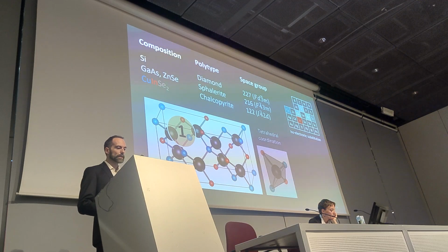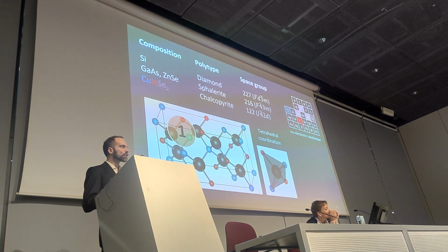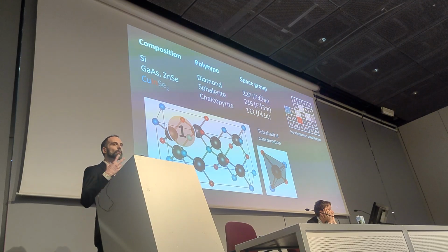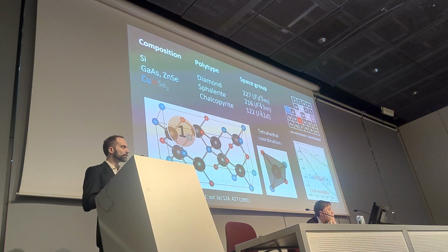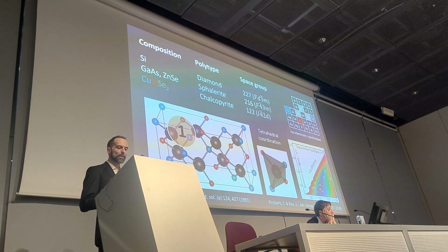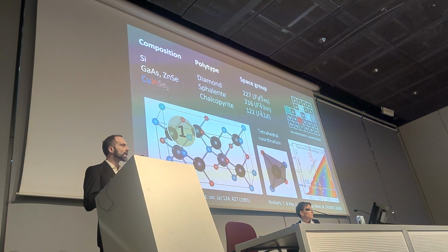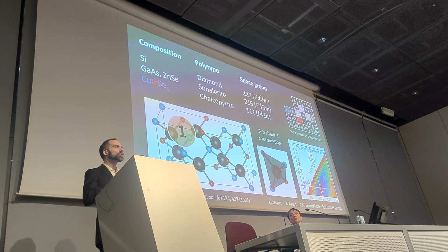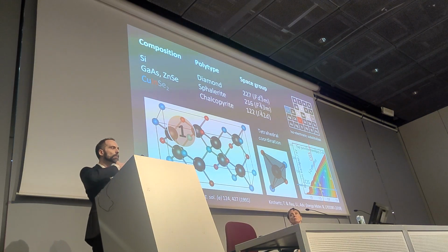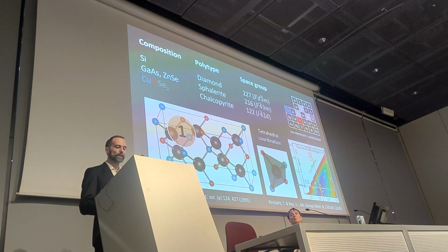Now, every atom in this structure retains the tetrahedral coordination typical for the diamond structure, and here we see a selenium atom coordinated by 2 copper atoms and 2 indium atoms. The very same structure also holds for the copper indium gallium diselenide, so we can replace indium with gallium in a complete miscibility range. And this is important technologically speaking, because the 2 end members, copper indium diselenide and copper gallium diselenide, have a band gap that matches precisely the highest efficiency Shockley-Queisser limit for a double junction configuration. So in a double junction configuration, in principle, we could couple 2 absorber layers, one on top of each other, to harvest better the solar radiation and reach, imagine, a 45% power conversion efficiency in principle.